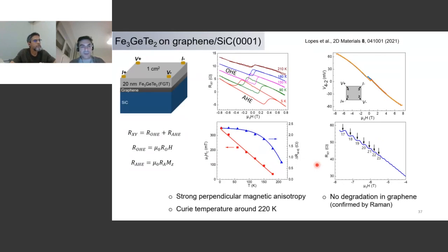So quite quickly here, we investigate transport in these materials, and we could obtain results that are the same as this state-of-the-art flakes. Basically, we have the anomalous Hall effect here, and when we do this transport, the resistivity is a sum of the ordinary Hall effect, that is basically a straight line, and this hysteretic part here that is due to the anomalous Hall effect taking place in the ferromagnetic metal. Based on this information, we are able then to plot, for instance, the magnetic coercive fields that we have for different temperatures, as well as the anomalous Hall resistivity. And we can plot that as a function of temperature. When these two properties go to zero at a certain temperature, that is the temperature that you can take as the approximate Curie temperature, which in this case is around 220 Kelvin.